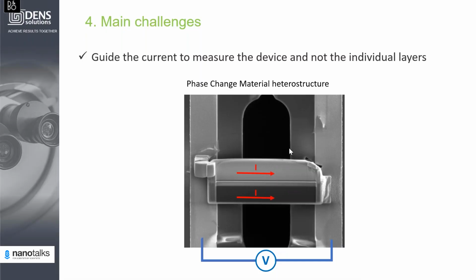Another limitation concerns the path of the electrical current. Basically, when you measure a device, quite often it's a heterostructure. And for heterostructures, to be able to use them, the current needs to go perpendicular to the interface. However, if you don't do anything, you will be measuring the individual layers. So as you can see, if you don't do any additional steps and you apply voltage to it, the current will be going through the individual layers.